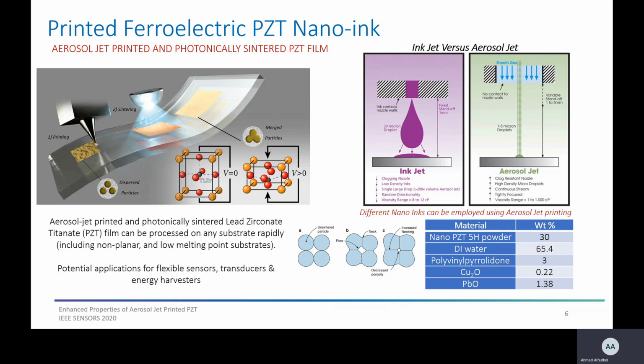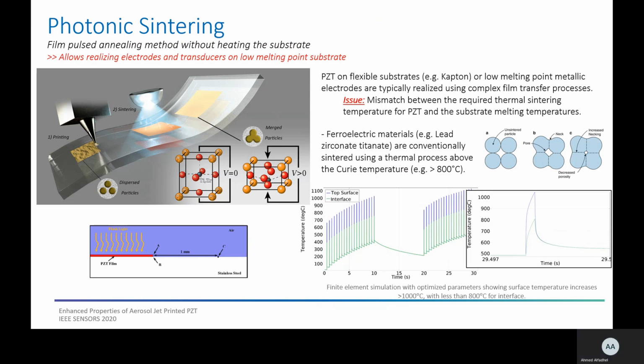Also, by having small particles, we can increase the packing of the PZT in the film, and the liquid phase aid acts as a lubricant and assists with the reorientation. The optimized ink solution can be seen in the table on the bottom right-hand side. Stainless steel foil, capable of withstanding PZT sintering temperature, was used in this process, and that's both for photonically sintered and thermally sintered samples.